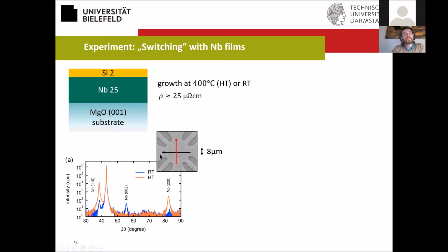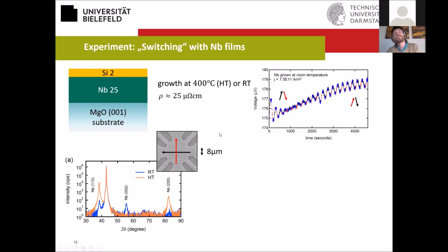Okay, then we did basically the same kind of experiment. We've structured these 8-arm devices. These are a little bit bigger in our case because we can't properly use electron beam lithography because these substrates are insulating, so they charge. So we avoided this by just using optical lithography here. And now we did a switching experiment. This is our niobium film grown at room temperature, and we pulse it in this experiment with 7.5 times 10 to the 11 amps per square meter, and we find that we get a transverse response, very similar to what I've shown you before.